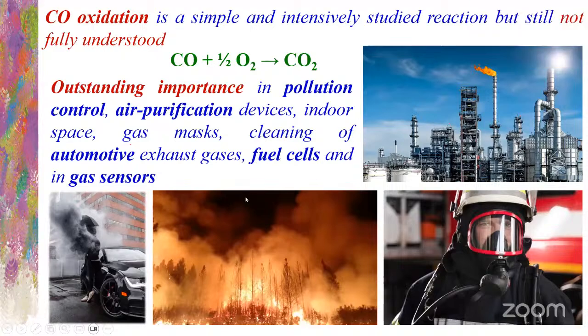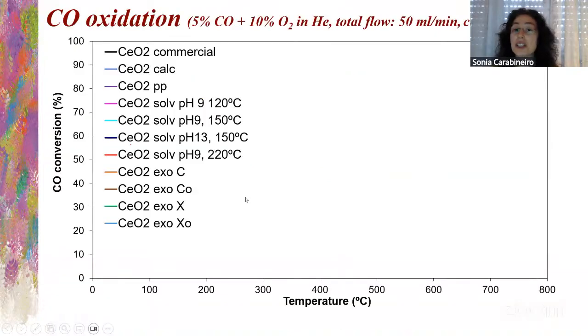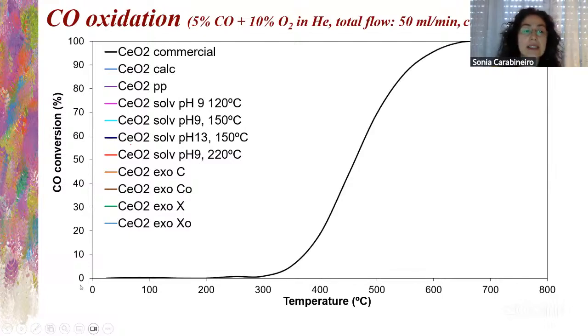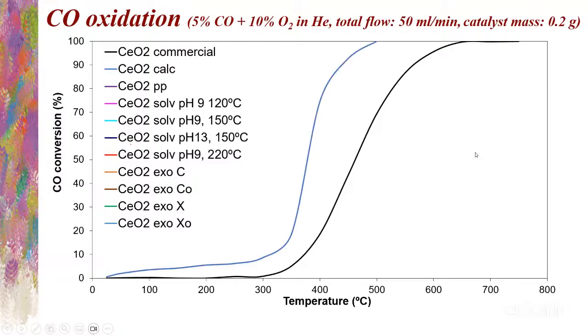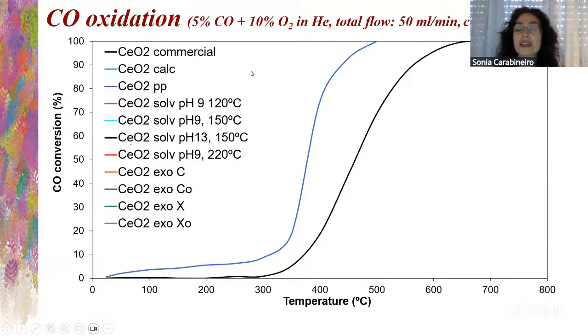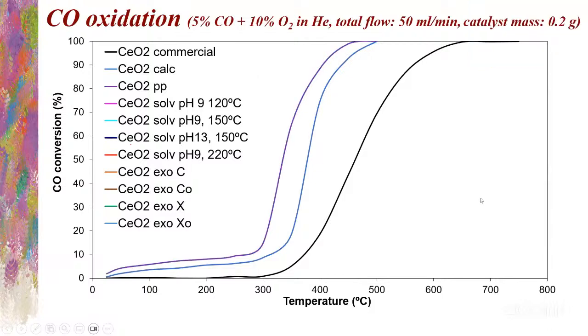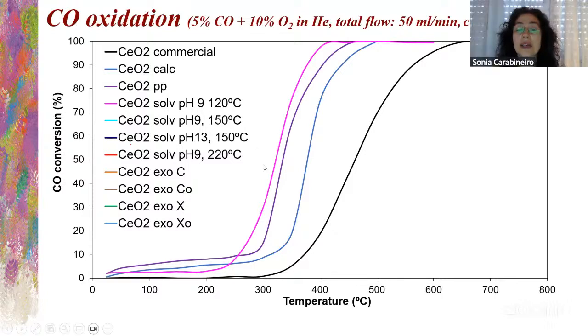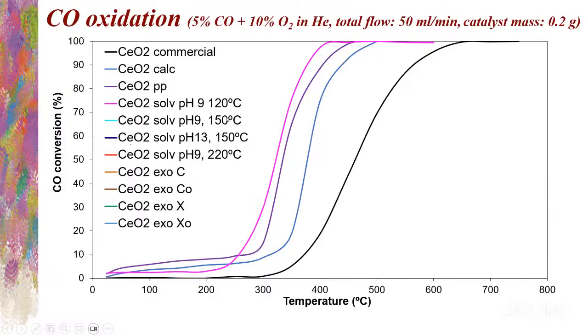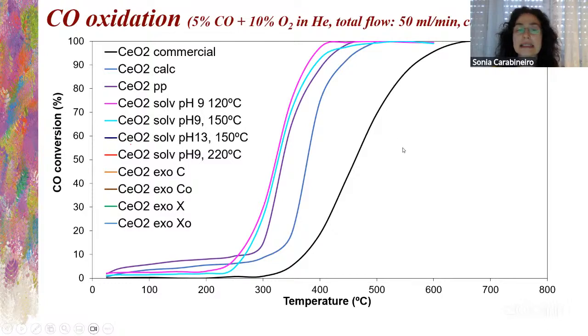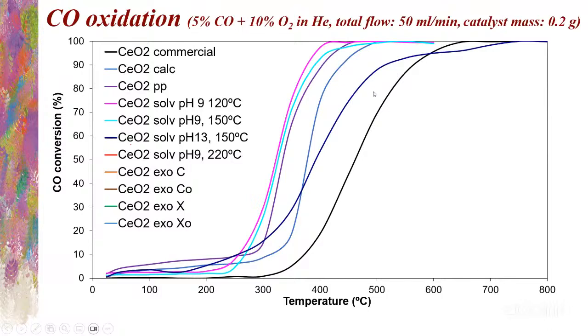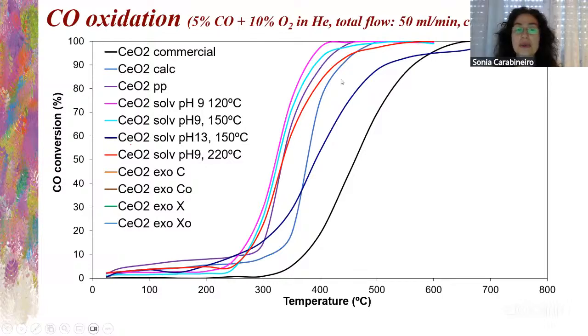And if we compare here the CO oxidation for all the samples, here we have CO conversion versus temperature. So we have here the commercial series. If we compare the calcined series, we see it's better because it achieves full conversion at lower temperature. If we compare the precipitated series, even better. If we compare the solvothermal series at pH 9, we know it's better. But if we increase the temperature, what happens? It's a little worse. If we increase the pH, it's much worse. See, not good to increase this pH. And here, if we increase the temperature, also a bit worse. So the best value is this one, 120 pH 9, okay, solvothermal.